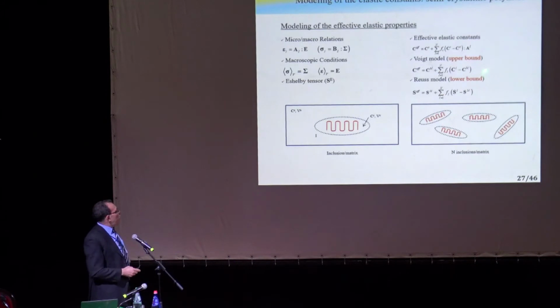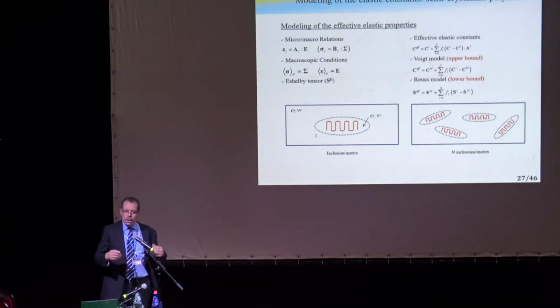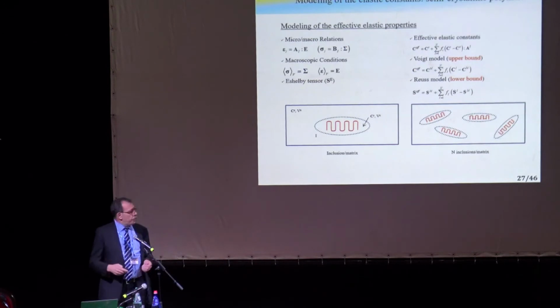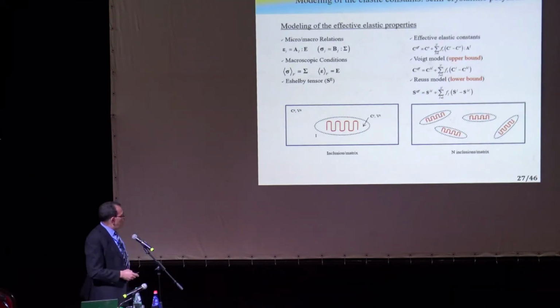So if you take the upper bound or lower bound, this is just averaging. If you want to calculate the effective stiffness, it's just the sum of all stiffnesses. And here the same thing. But now what is the inclusion to consider? We can think of a double inclusion where we have the crystal surrounded by an amorphous phase. And there is a paper by Hori and Nemat-Nasser that explains that model well, which we can apply.